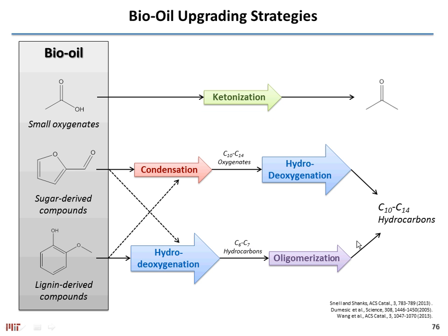So the concept that we're pursuing is what the guys at NREL actually call ex situ catalytic pyrolysis. So this is a depiction of a reactor. You have your biomass over here. You feed it in this downflow reactor, or in this case, this is an auger reactor. So you feed it over here through a twin screw extruder that is heated, and you kick out the bio-oil as a vapor over here that you eventually quench and separate over there from the solids. So the question here is, can we intercept the vapors here before quenching? While they are hot and you are working at temperatures of about 300 to 450 degrees C, can we work in this temperature regime to do some of this HDO chemistry before we quench it? I'm sorry about this. I didn't know I had this animation.